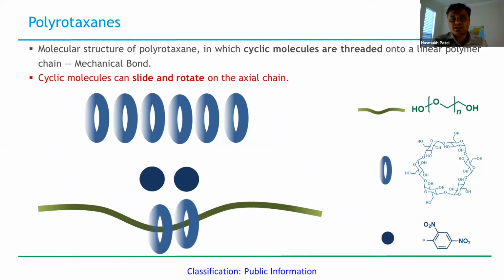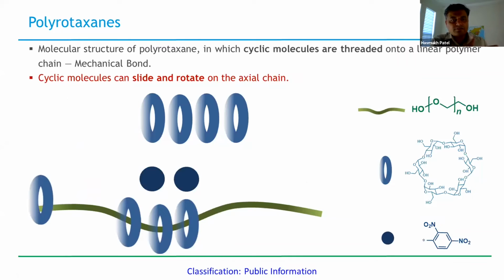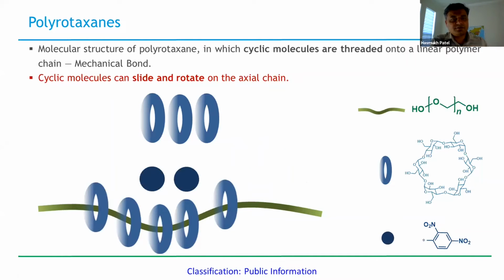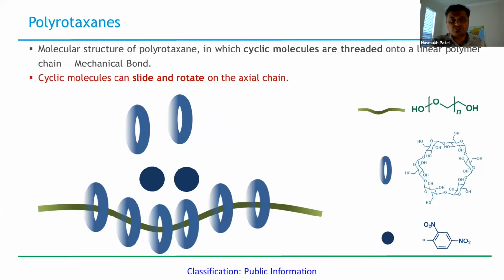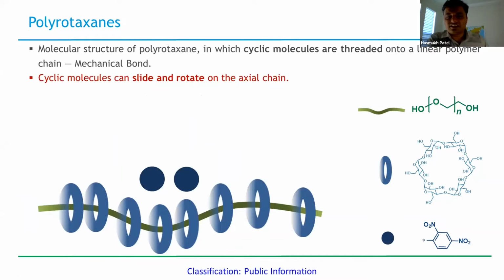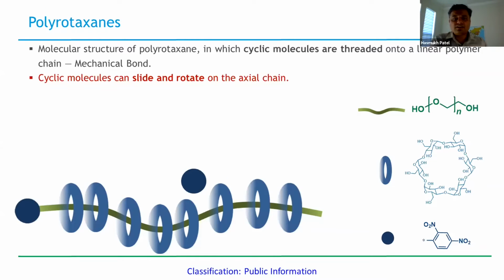Basically, if we mix polyethylene glycols and alpha cyclodextrin in water, it immediately forms the host-guest compounds. The cyclodextrin rings start threading onto the linear chain, and once we have the cyclic molecules threaded onto the linear polymer chain, we cap it from both sides so that the cyclic molecules cannot escape from this necklace-like structure. So this is called the Polyrotaxane, where we can have the rotation of these cyclic molecules as well as the sliding of the cyclic molecules.